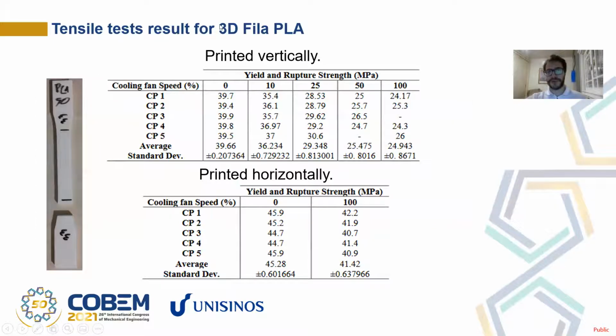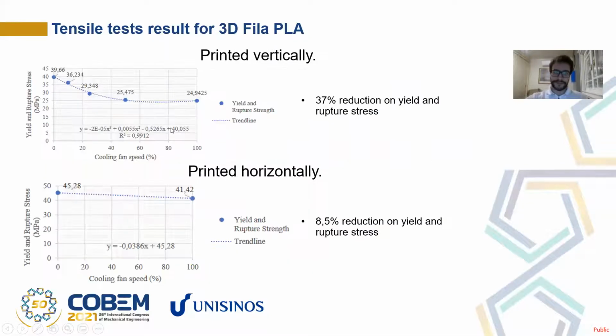And here are the results for the 3D Fila PLA, where we can see that for the parts printed vertically, between the cooling fan turned off and on at the maximum, there was a reduction of around 37% on the yield and rupture stresses. And for the ones printed horizontally, the difference between the cooling fan turned off and on at the maximum was around 8.5% reduction on the yield and rupture. In these two tests, the yield and the rupture points were the same, so when the part reaches the yield point, it ruptures.